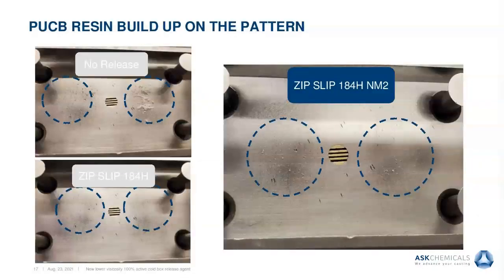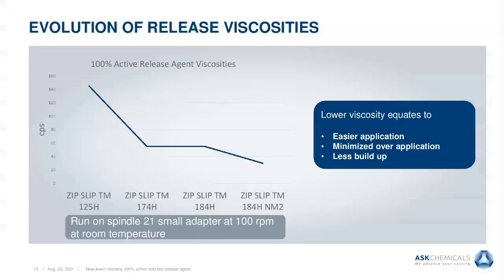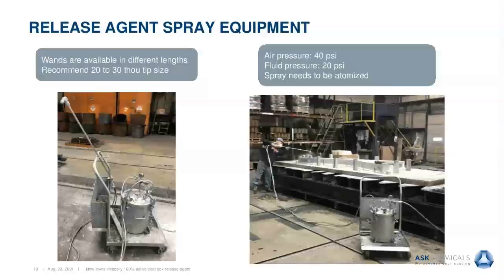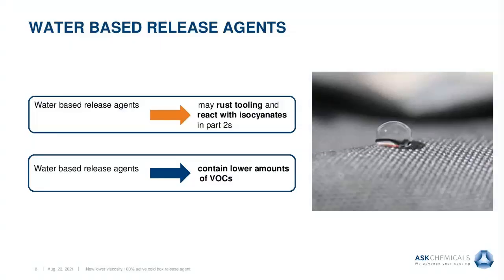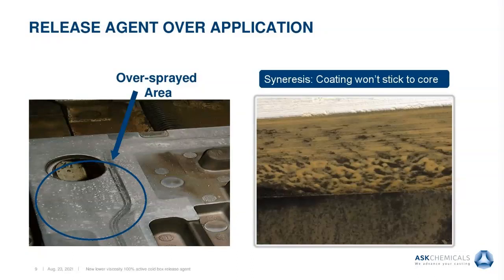Back to that slide, and I'll show you again. This is where the coating pulls away from the core. It's right here. This picture on the right. That's where coating was applied, but you can see that you don't get consistent coverage. And if you can see the sand grains through the coating, then you've put too much release agent on.